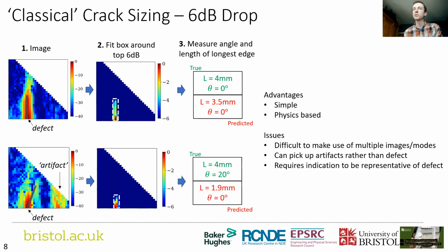And hopefully deep learning can step in and do a better job at sizing it. So while this is a simple and physics-based approach, it's difficult to make use of more than one image, and in fact, nigh on impossible to do it in a useful way. You can also pick up artifacts rather than defects. What I mean by artifacts is here we've got this indication, which is actually a response from a different modality. This is a shear image, and this is actually the response from the longitudinal conversion that just shows up in the wrong place.